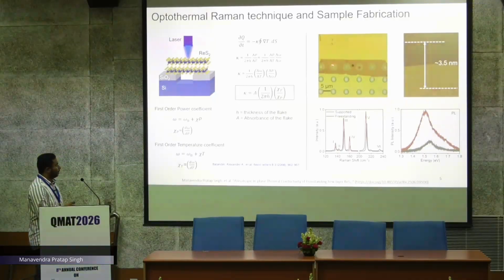This is the sample. This is a trilayer of ReS2 suspended on an array of holes. We can measure at 5 places here. The thickness is around 3.5 nanometers. We can see that it's well suspended, and supported and suspended regions have some difference due to the in-plane strain, and PL is also enhanced in the suspended case, which shows it is well suspended, and we can study it with this optothermal Raman technique.